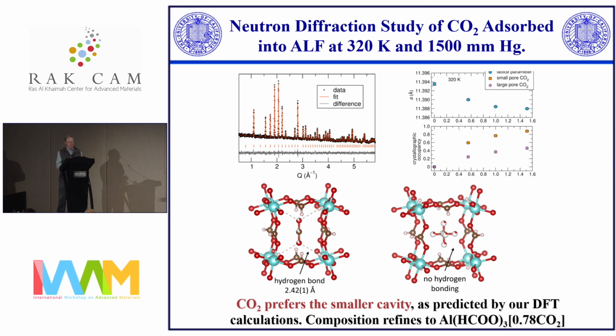We did further detailed neutron studies on the location of the CO2 in the two different cavities, the smaller cavity on the left there at the bottom, where the CO2 is absolutely perfectly sited for hydrogen bonding between the oxygen of the CO2 and the hydrogen atoms of the formate linker. And so that's really tightly bound.